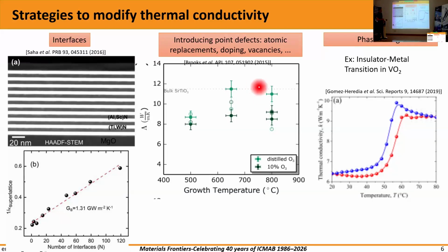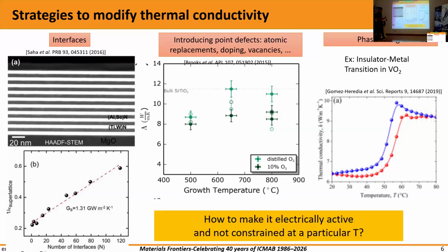Another way is also with the phase transition. If the two phases have different thermal conductivities, if you change from one phase to another phase, then you're going to have a different thermal conductivity and thermal current. But then the question is how to make them electrically active. So how can we change that with an electric field? That is because all these materials are fixed or constrained with a temperature, as in vanadium oxide. So how can we make them electrically active?